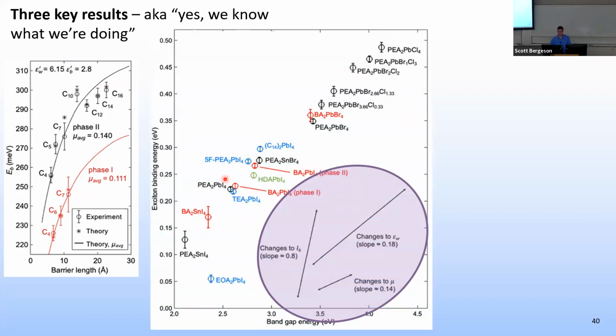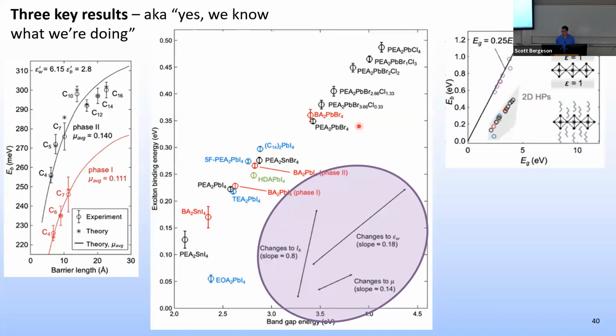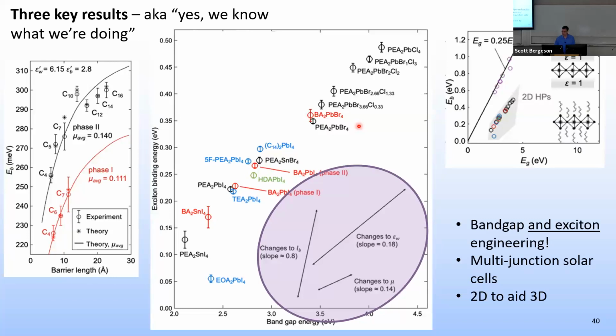Here's that plot from before of all of the materials we measured. By varying parameters systematically in this theory, we could tell that the three most important parameters are actually the excitonic effective mass, the well dielectric constant, and the barrier length. And we could predict what kind of changes those are all going to make. And so if we want to get a particular band gap energy and a particular binding energy, we know how to tailor the material to do that. I think I'll skip through that because time is getting short. But this gives us not only the capability to do band gap engineering, but also exciton engineering.